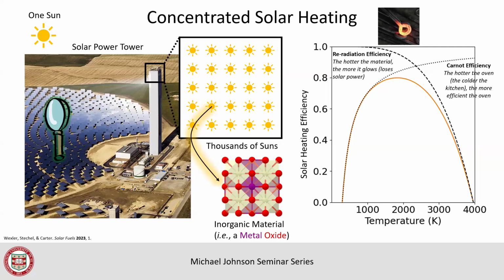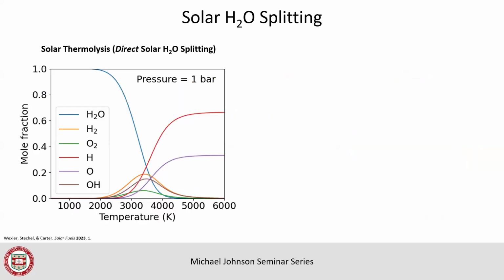You've got two competing efficiencies. Say you were to work with this particular solar power tower station, you could get about 80% efficient conversion of that solar energy into energy that could do the chemical work of water splitting. Which isn't bad, actually. I told you before, we needed 225,000 watts, that's how much was actually hitting our house. We only need 1,200. 80% of 200,000 is still way more than enough, right? So that's not a problem, actually. This is for a specific architecture where the intensity of sunlight is 10,000 suns.